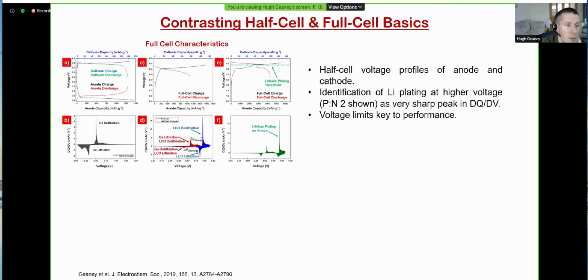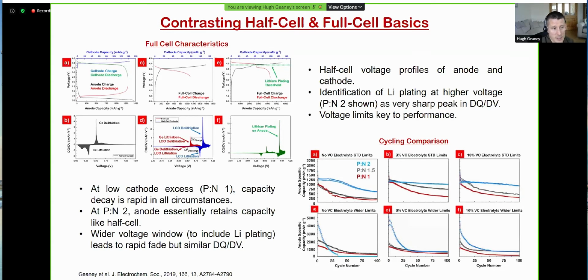And what happened essentially is just above 3.9 volts, if you continue to charge the battery, you'll have this secondary plateau here, which we found is due to lithium plating. So what can happen is you can have a secondary process beyond your standard lithiation where you have lithium plating. And as I've highlighted, that's a major issue in terms of full cell operation. So again, I'm conscious of the time, so I can go back and discuss the intricate details of this if people like. It's just to get across the main points of these. So what I did then was look at the cycling comparison of the different setups.